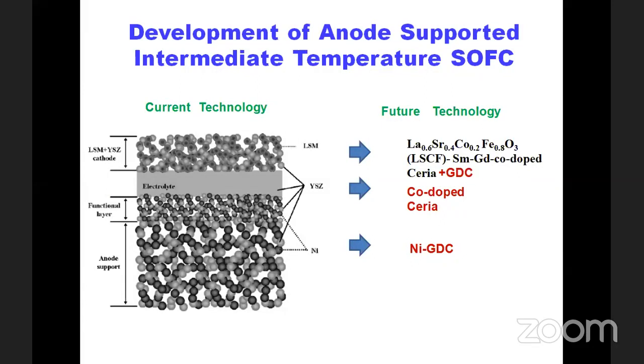What we tried to do is, we have taken gadolinium doped ceria as the electrolyte, and also nickel gadolinium doped ceria as the anode, and the lanthanum strontium cobalt iron oxide system, LSCF in short form, doped with a certain amount of GDC as the cathode. This kind of combination we proposed and made ourselves, structures which can be operated in reality at intermediate temperatures. So this is a very interesting and very important area in energy conversion technologies, all through electrochemical means.